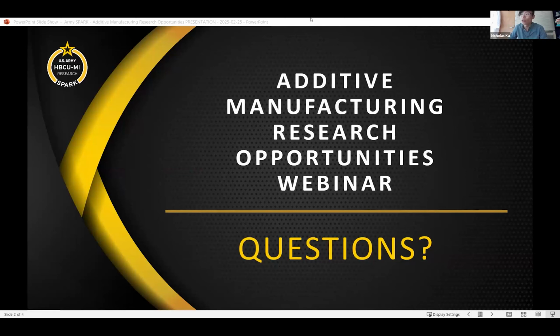Also, we're looking at carbides and borides, and a lot of the time a carbon source is needed as a sintering aid. So being able to tune the chemistry to get the char yield we want is something we've always had an interest in, but we've never really had the chemistry background for it. That's another area of interest: tuning binder chemistry to give us the sintering aids we would want in our ceramic processing as well. So just food for thought.